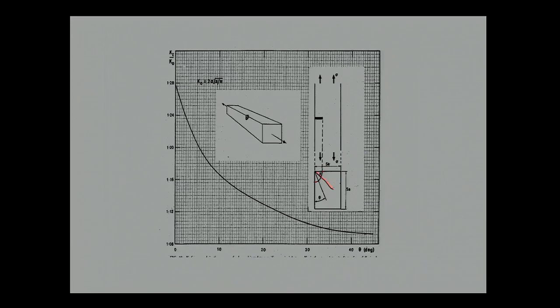That's not very good 45, but take it as a 45, right? So as the angle gets smaller, basically as you move toward the edge, this gets bigger and bigger. The K1 over K0 gets bigger, and then eventually it reaches 1.28 at the edge. So of course going the other way toward the other surface is the same.